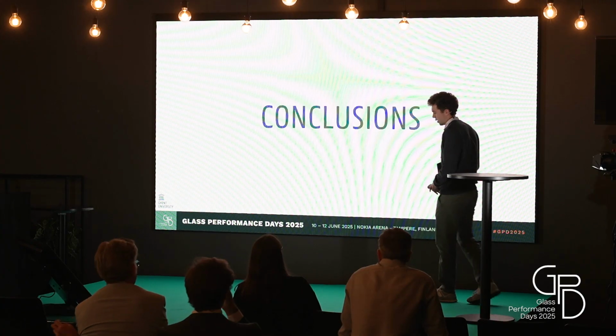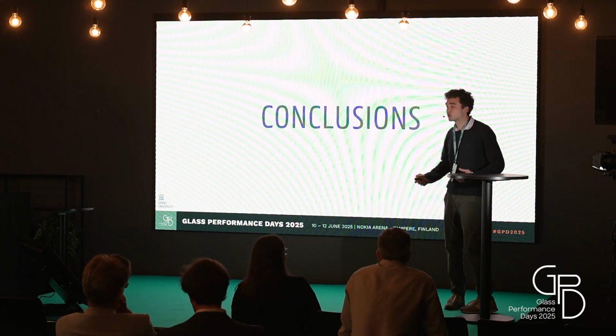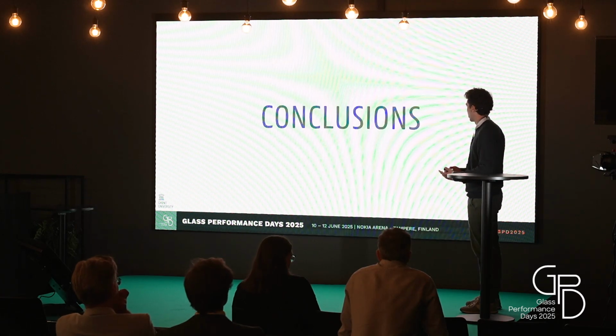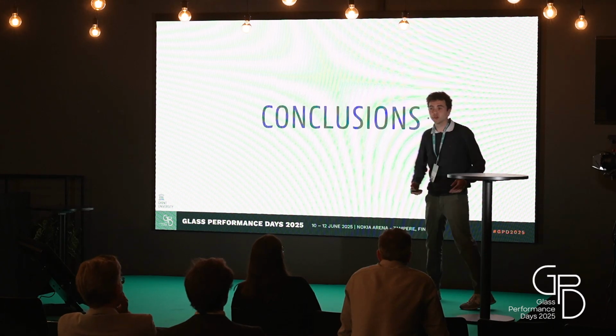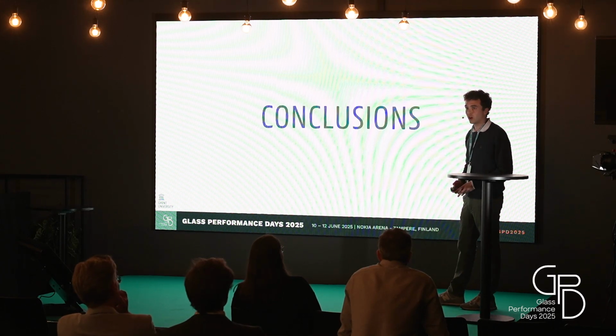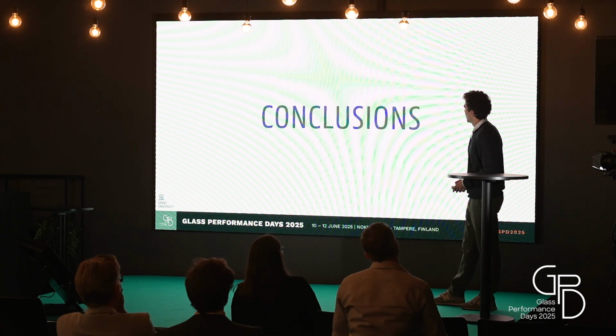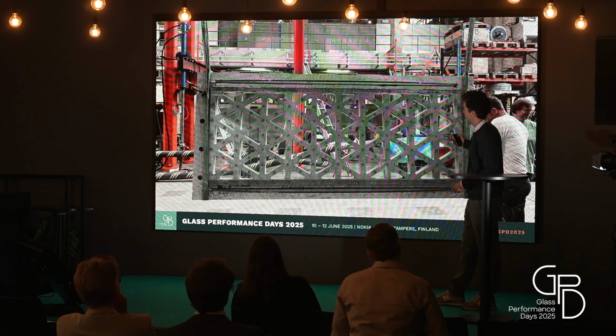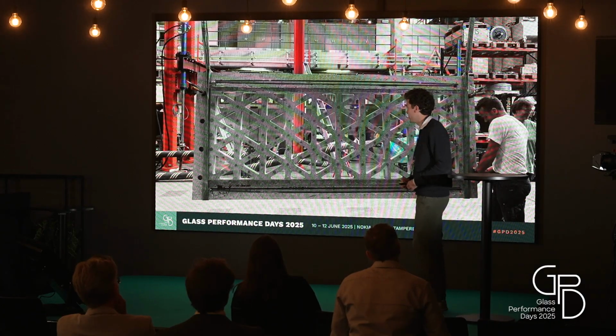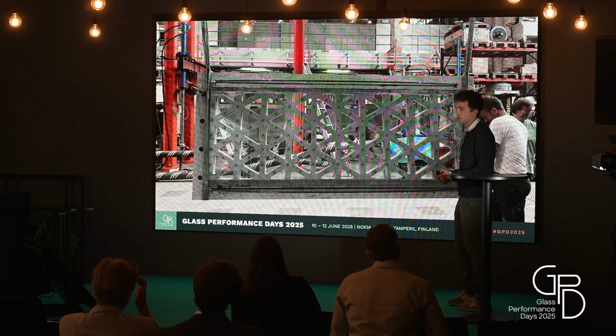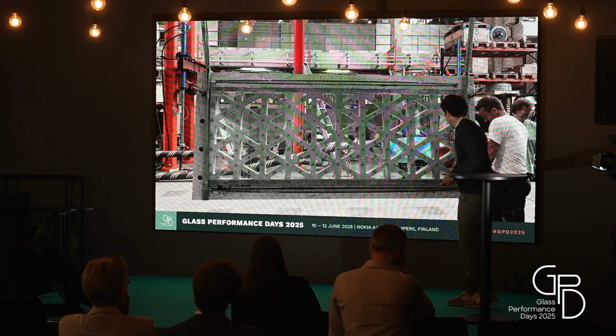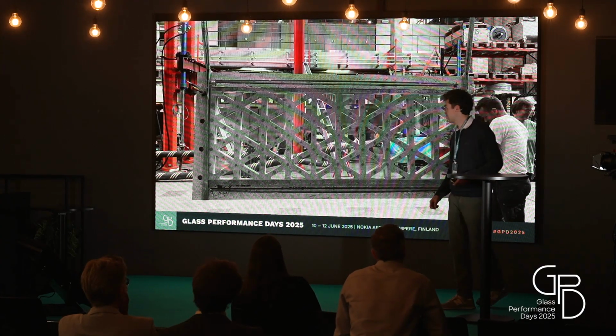So some conclusions. Because it was the first actual full-scale glass to concrete model or showcase that we made, there were quite some challenges during the production process. Really quite a lot, but I will give only 3 of them here. First one: we're working with quite heavy and big elements, and on top of that, we're also bonding a very brittle material to it, the glass. And because of the bonding techniques, we also have to rotate it quite a lot, put it upwards and then lay it down, for example to fill it with epoxy for the fins, and then also to place it on the frame. So it was quite a lot of handling.